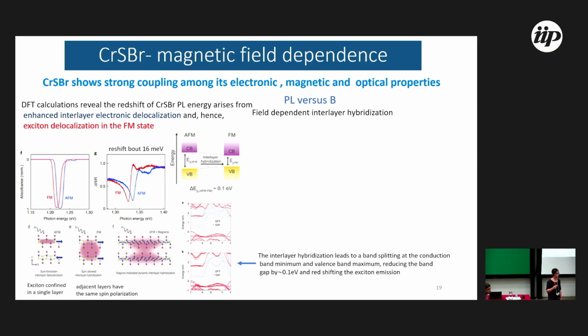So now you're placing the TMD on top of this? Not yet. Now I'm just doing some revision about these properties, because it is important to know before I put the TMD. I just would like to say that the gap of CrSBr depends on the magnetic order. Antiferromagnetic is higher energy, ferromagnetic is lower energy. The gap, this is an unusual property. I think only this material has this property. You can change the gap with the magnetic order.